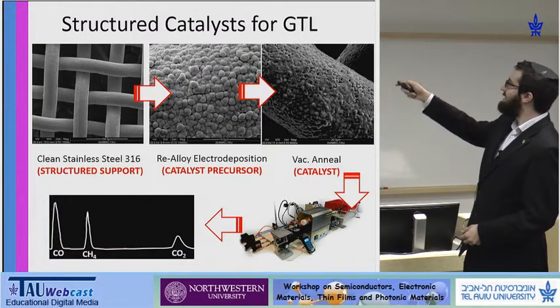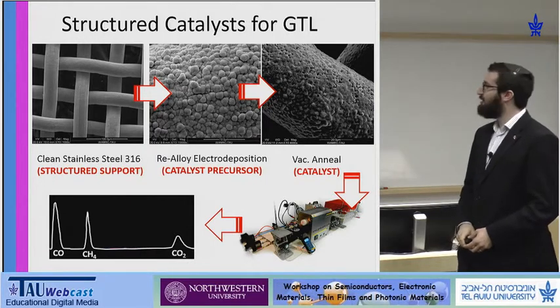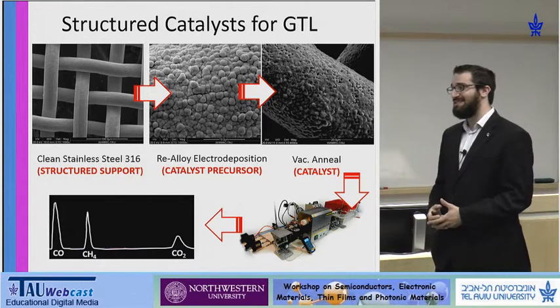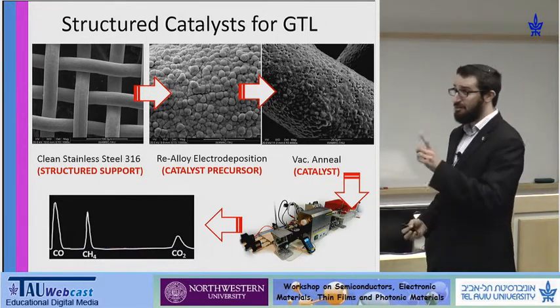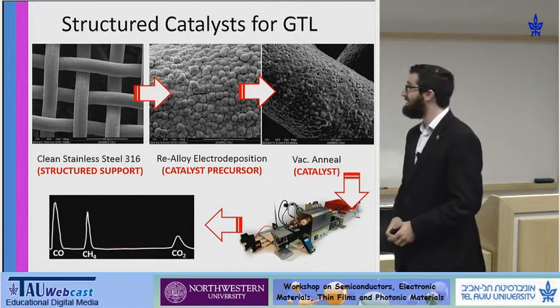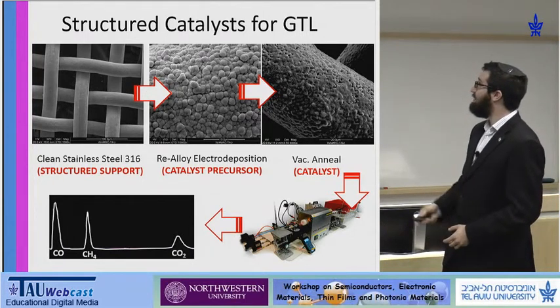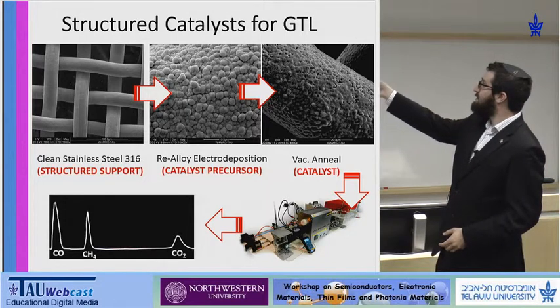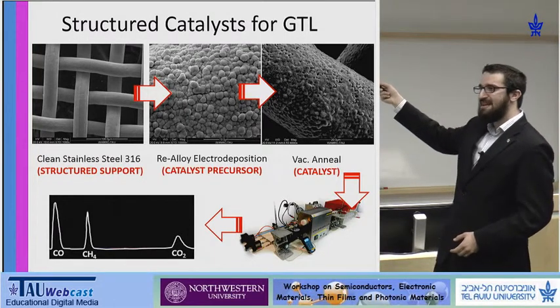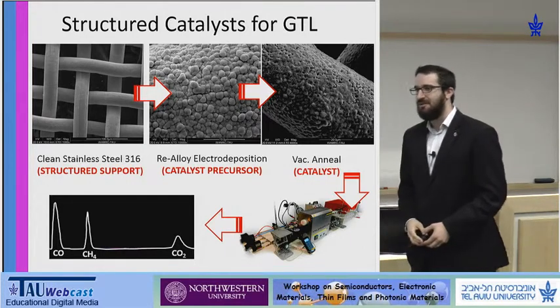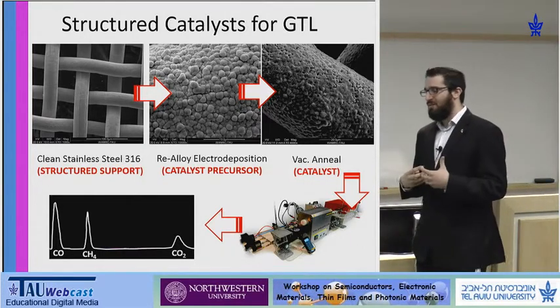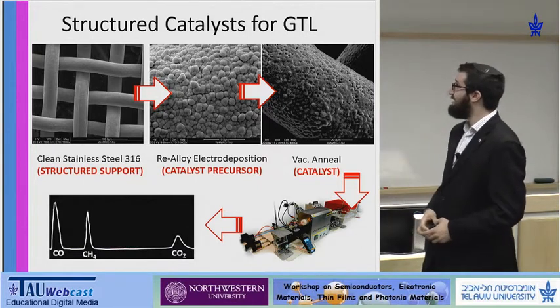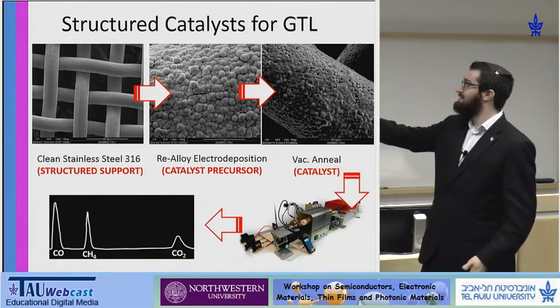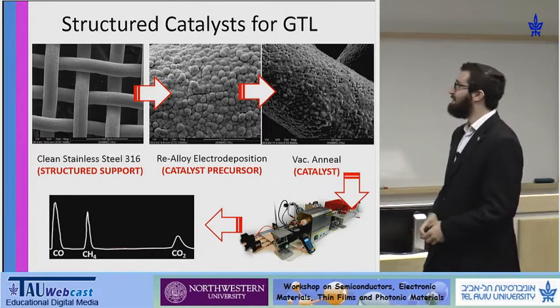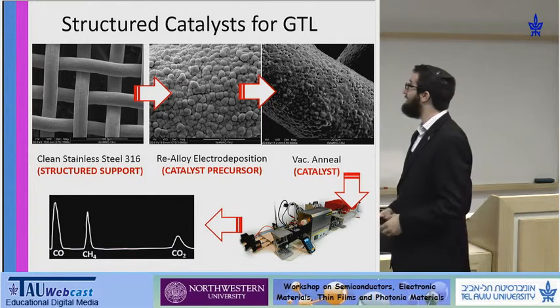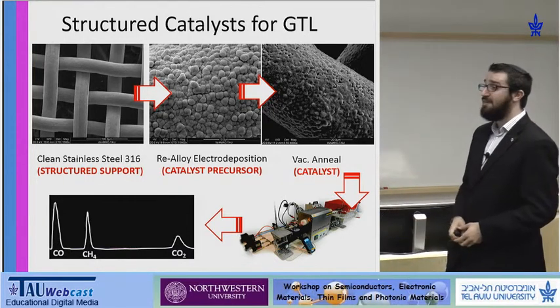We do vacuum annealing in addition to a few other thermal treatments. And what this does is there are volatile phases, nickel oxides, nickel hydroxides, including rhenium oxide, by the way, which has a non-zero volatility at our temperatures. And what we get as a result, not this nodular surface, but rather this very porous surface. From the top down, it almost looks like a metal sponge, which is very intriguing because this means we can come up with a very highly conductive film that can have a surface area much higher than simply the mesh, maybe not as high as a powder, but this highly conductive film that has what I'll call an intermediate surface area due to its porosity is very intriguing.